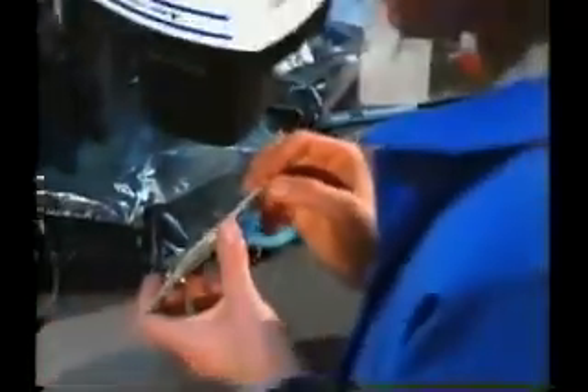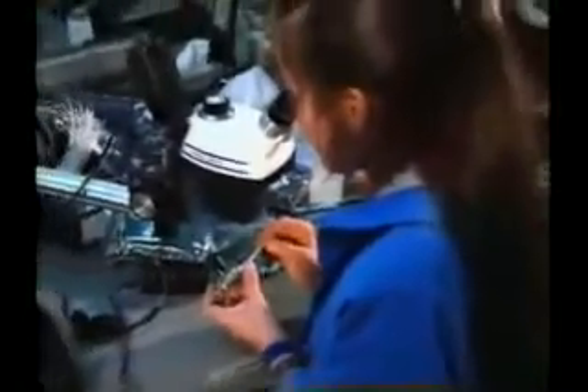But some heat damage may not be visible on the surface of the board. Excessive heat has caused a crack in the plating on this through hole. Differing rates of expansion for the metal platings and the laminate materials have caused this interior crack. This sensitive component was also damaged by excessive heat.